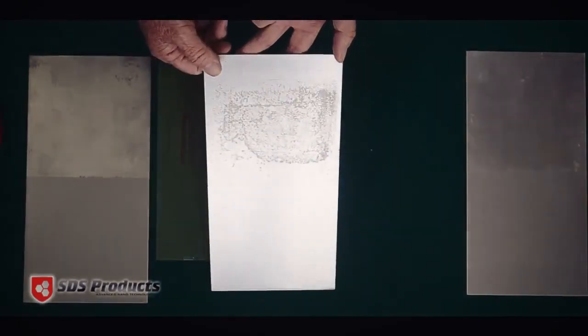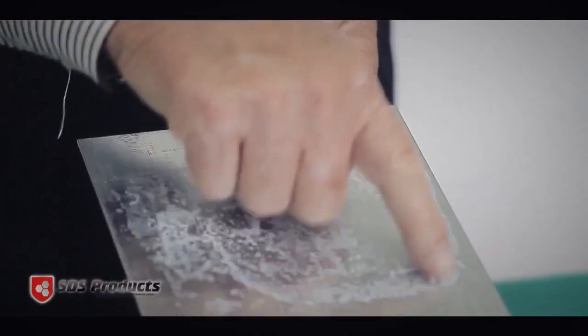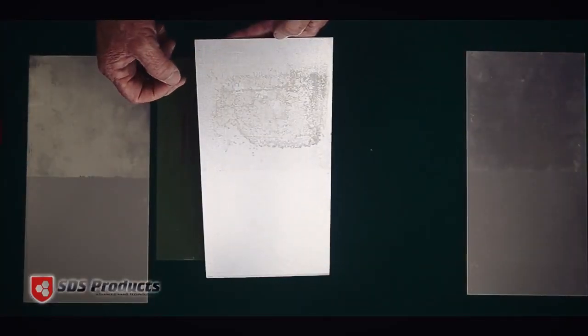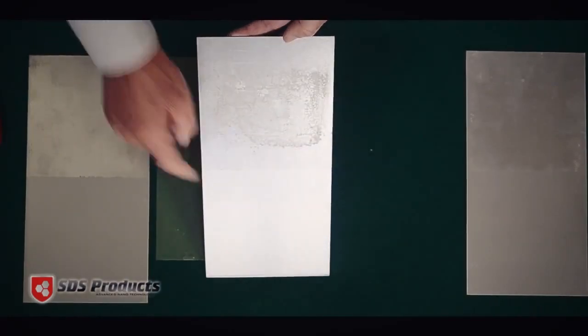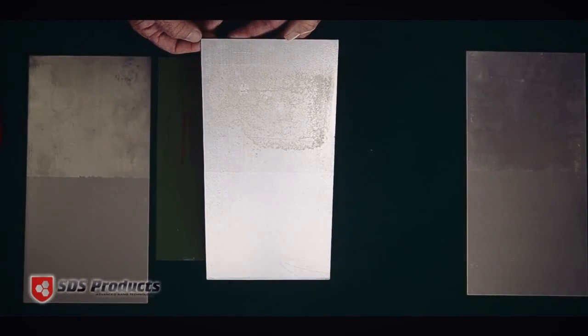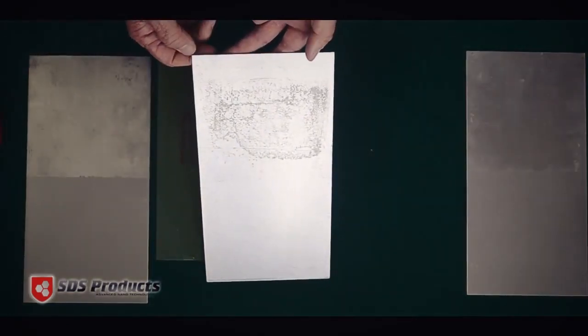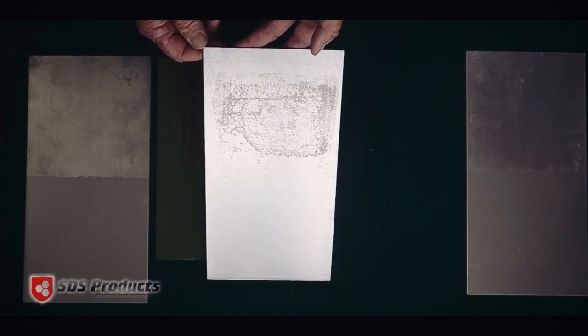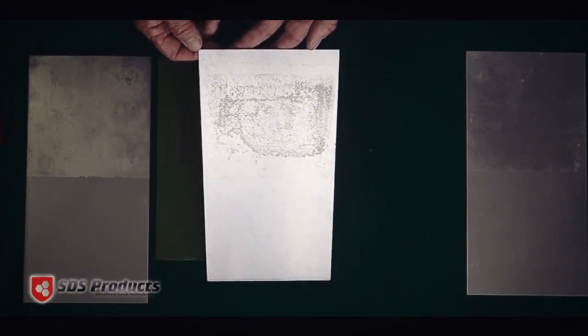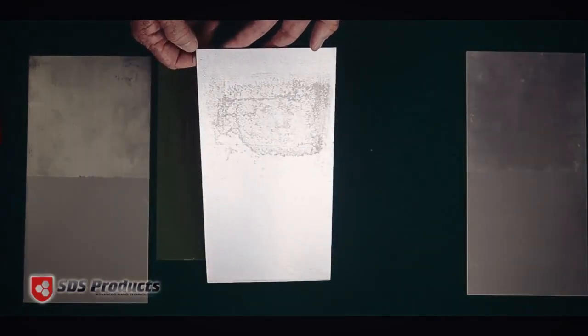So this developed white rust. If you were to do this in a corrosion chamber, salt fog corrosion in UV, you would develop white rust on the untreated galvanized in 26 hours. The coated side doesn't develop any white rust for 864 hours. So from 26 hours of seeing white rust to 864 hours. 864 hours in a salt fog chamber test is almost 9 years time. Every 100 hours of testing equals a year. So we ran this for 1,000 hours. No red rust. We ran it for 1,200 hours, 12 years, no red rust. The untreated side, we developed the white rust in 26 hours. We developed red rust in 136 hours.